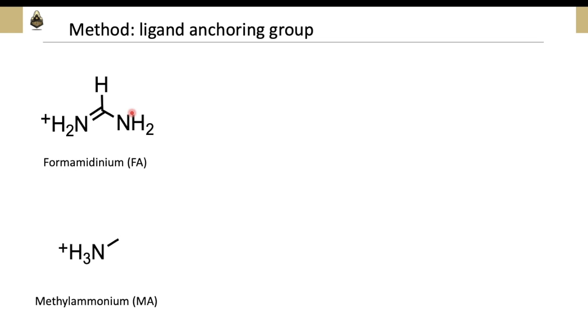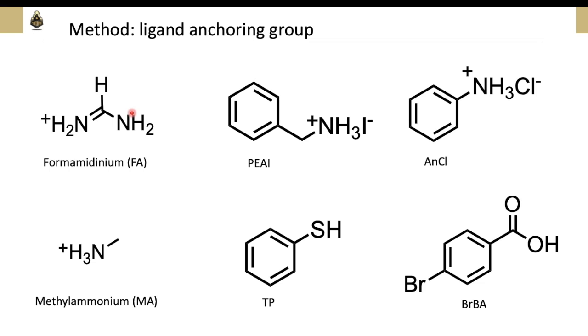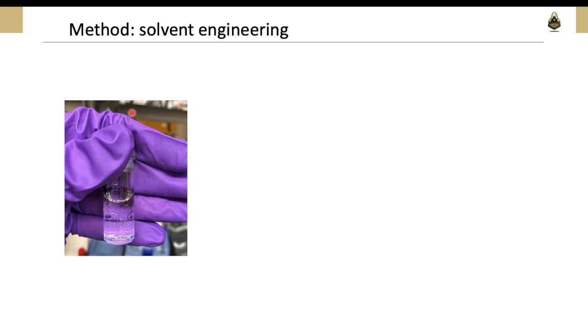In the literature, different types of anchoring groups are being studied. Here are a few examples. My research group has synthesized the pi-conjugated oligothiophenol ligands with FA anchoring group that can be applied on our perovskite layer. The FA anchoring group is a unique idea, and we believe that it will match the FA vacancies in the perovskite structure. As we change the ligand structure, the solubility also changes. Therefore, we need to find a good solvent system for these ligands.